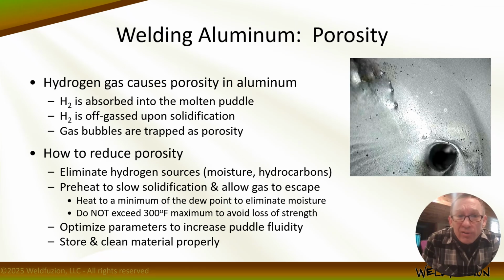The next thing you want to do is eliminate any hydrogen sources, primarily moisture, humidity, and any hydrocarbons. It's commonly recommended to first degrease your aluminum and then proceed to oxide removal, or you risk smearing around those greases instead of actually removing them. Oxides can be removed with chemical or mechanical means prior to welding, and they often employ, as we mentioned before, DC electrode positive or AC current for cathodic arc cleaning action or etching around the weld.